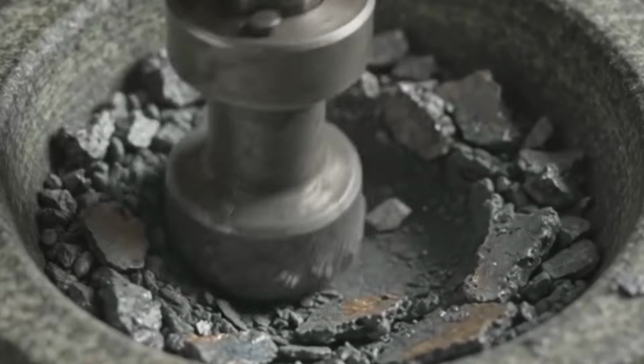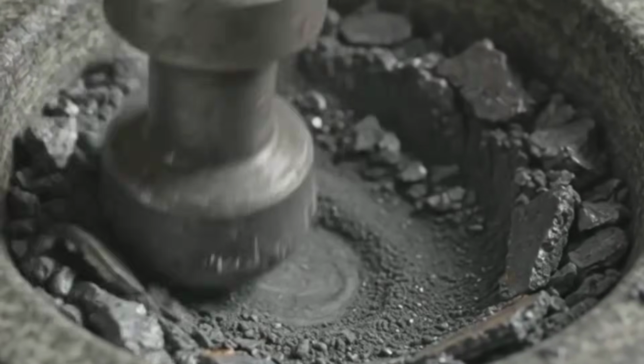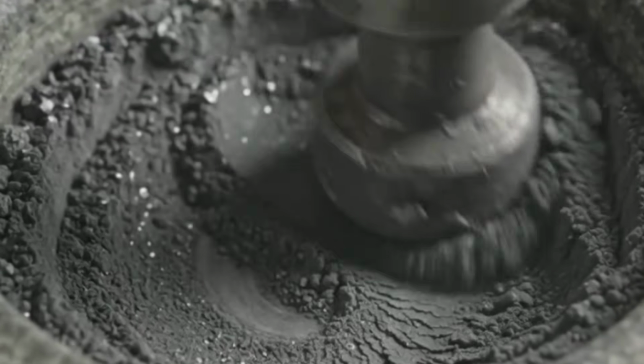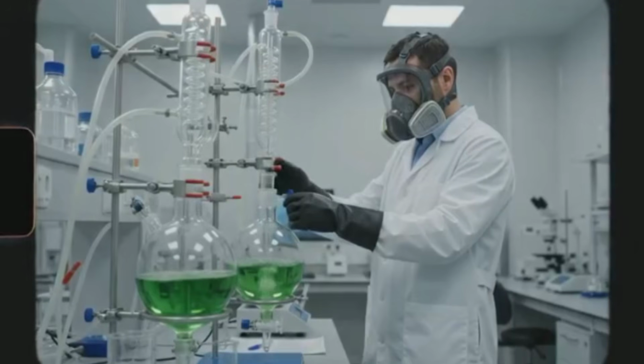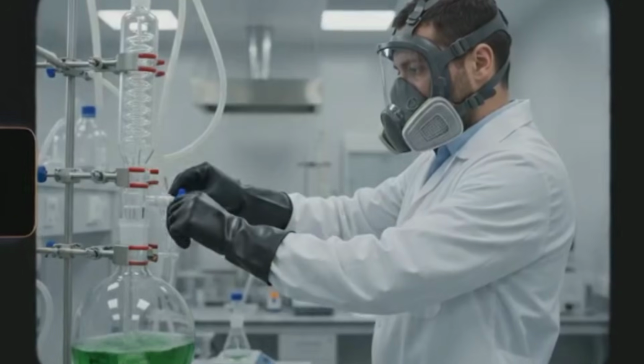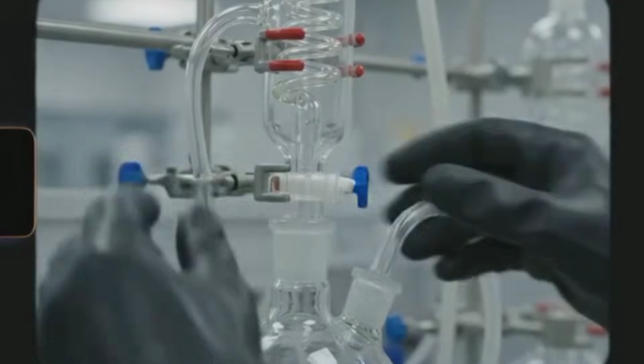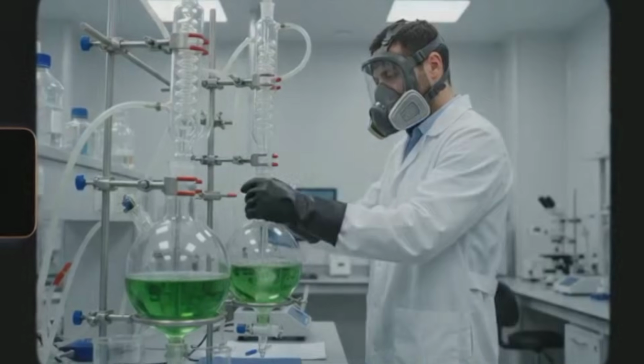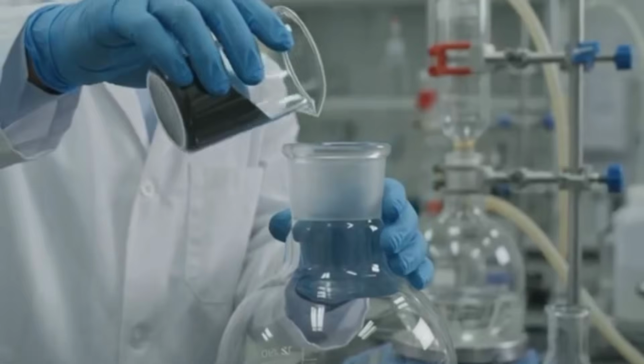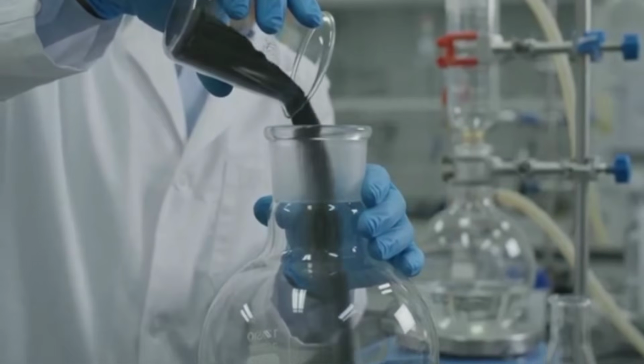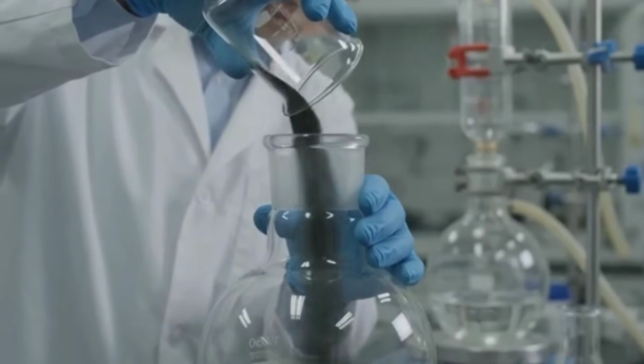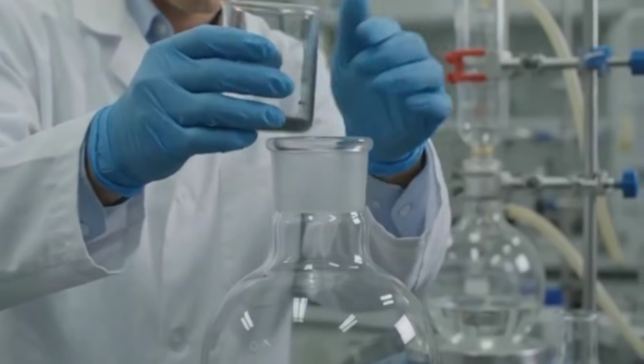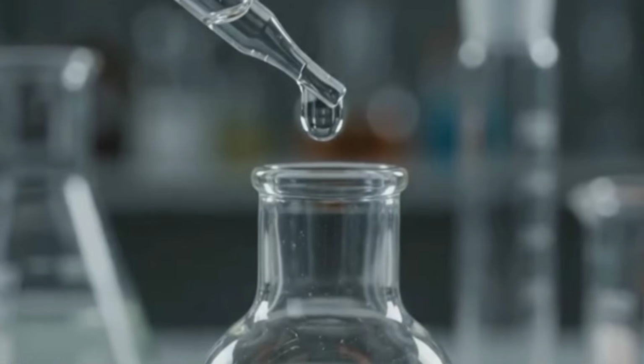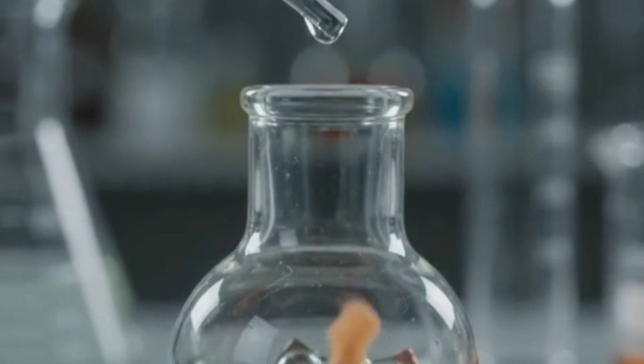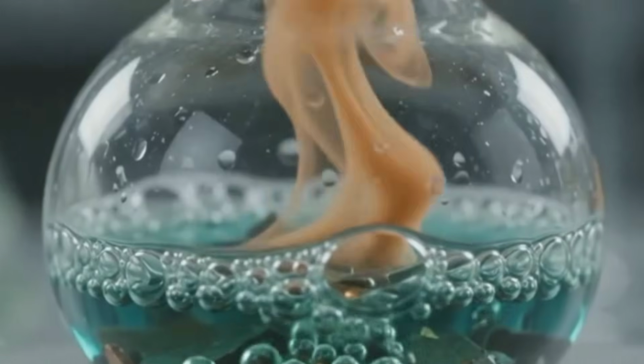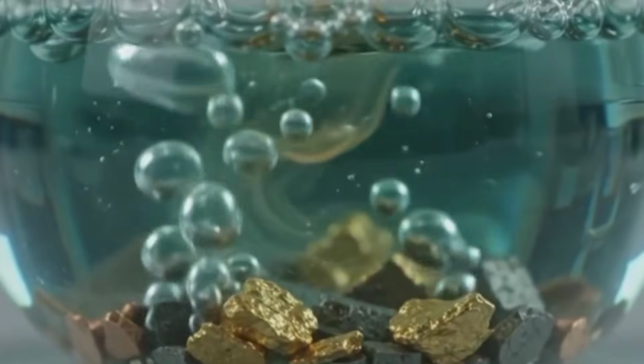The cooled metallic ash is pulverized into a fine powder, maximizing its surface area for chemical reactions. Inside a controlled laboratory environment, the chemical extraction phase begins with strict safety protocols. The fine metallic powder is carefully measured and transferred into the chemical reactor vessel. Nitric acid is introduced to dissolve base metals like copper, nickel, and iron, leaving the gold untouched.